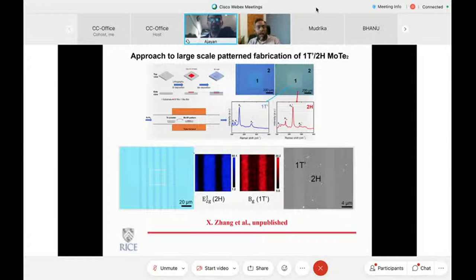So what we did was we essentially patterned tungsten underneath the growing layer and then did the growth. So the tungsten diffused into the molybdenum telluride during growth and essentially formed these 1T phases. And you can see we can actually grow large area, periodic 1T prime and 2H structures in a periodic fashion. So these are the kind of nano engineering things that we do so that you can make scalable devices and scalable structures.